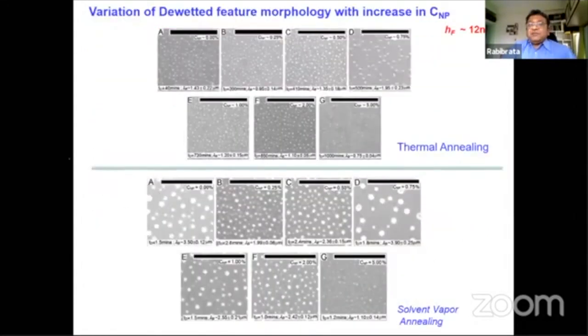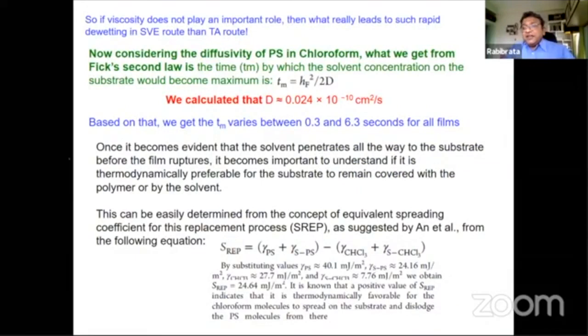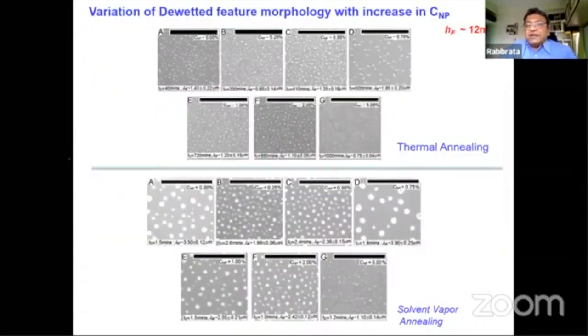So now the picture became very clear. So what was happening is in solvent vapor annealing, the solvent molecule was actually flooding the substrate. And the dewetting or the rupture, what you were seeing on the substrate, is of the solvent, and therefore it was so fast. And the polymer molecule was just sort of floating on top of these, in a dissolved condition, on top of this solvent layer. And it was just following the contours of the solvent molecule, right? So with that, we could explain the fast dynamics as well as the rapid dynamics.